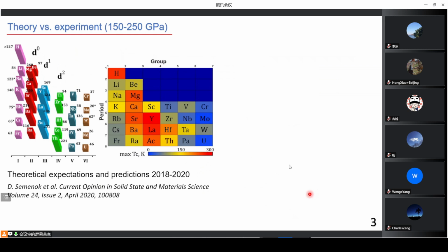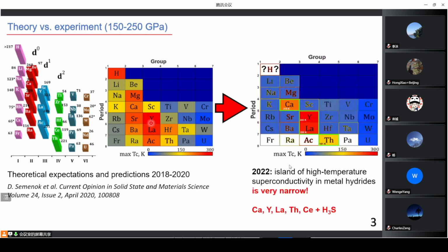So what's important? We can compare theoretical predictions made in 2018-2020. You can see on this slide this colorful map. It's the results of predictions: a maximum TC for different binary metal-hydrogen systems. You see it's very colorful actually. Yttrium, lanthanum, strontium, calcium, magnesium should give high TC, scandium, zirconium, hafnium, thorium, actinium as well. But these are predictions, and now in 2022 we can say that the island of high temperature superconductivity in metal hydrides is actually very, very small.